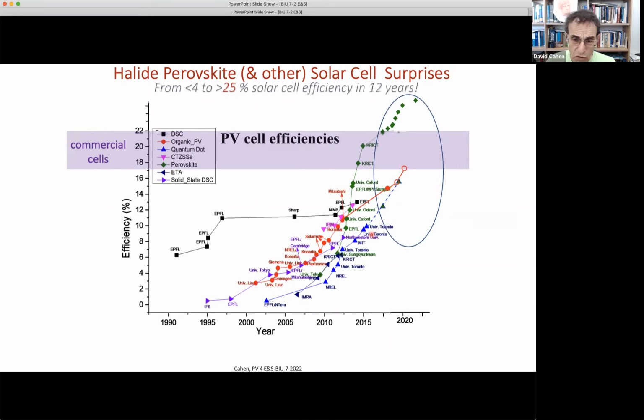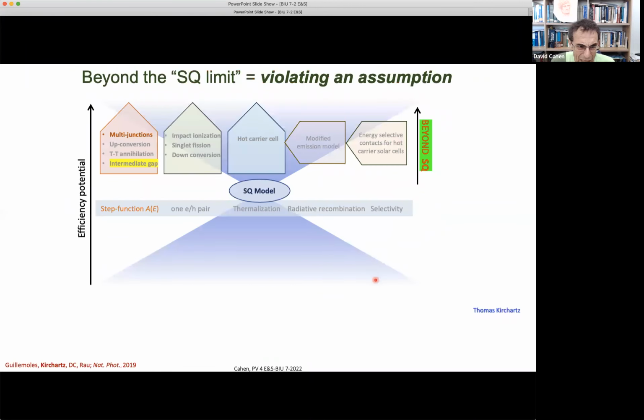And then there's also an impressive advance in quantum dot solar cells, but it has to do with the fact that the quantum dot solar cells are now made out of halide perovskites instead of lead sulfide. But you see, for the first time, these types of cells are getting into the band where commercial cells are performing. And that leads directly to one of the ways of violating an assumption, which is the multi-junctions. They are called tandem solar cells.